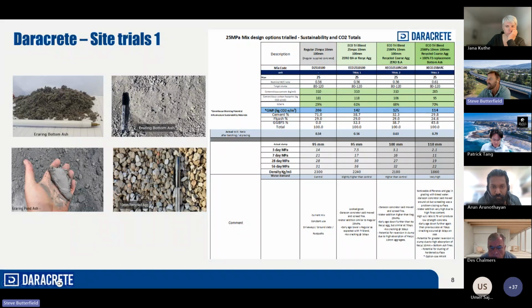The first mix is basically just a regular tri-blend, which most guys here in the technical would be familiar with. So it was just a tri-blend of basically fly ash, cement and slag. And the second one was a recycled coarse aggregate added to that same tri-blend. And then the third one, we incorporated the same tri-blend of slag, cement, fly ash with a recycled concrete, but also had 100% fine sand replacement with the furnace bottom ash as a fine aggregate.